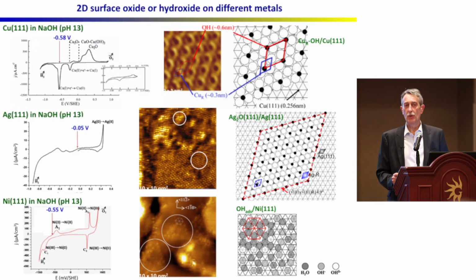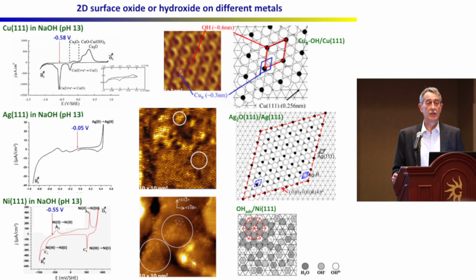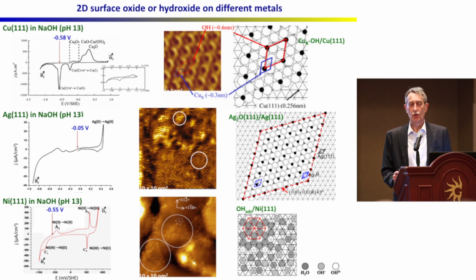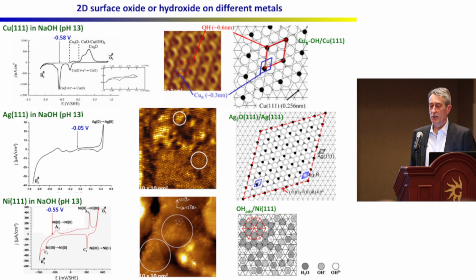So using these techniques, we look at a number of problems. And of course, if you are interested in corrosion, you are interested in what happens when you expose a metal to water. So the first question we wanted to answer was what happens if you take a metal surface and expose it to water? Do you get some sort of order at the surface, or do you have a completely disordered layer? When we started this work, most people believed at that time that because it was in water, everything was not well organized, so that it was essentially disordered. And we found out that this is not at all the case.